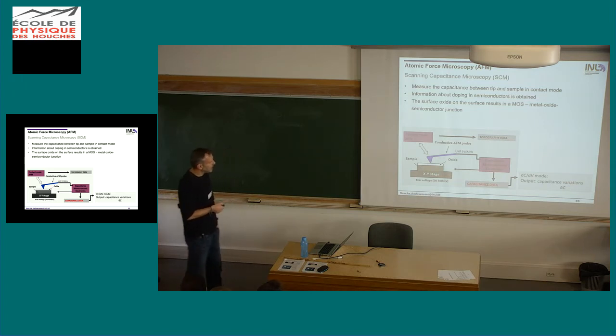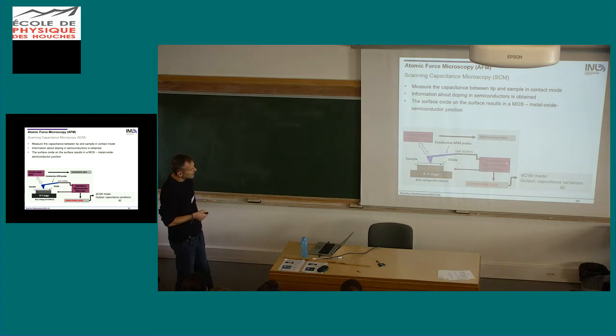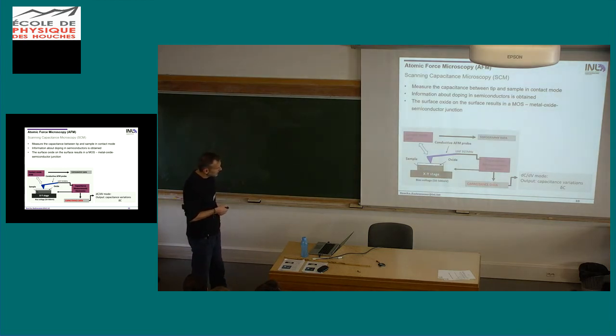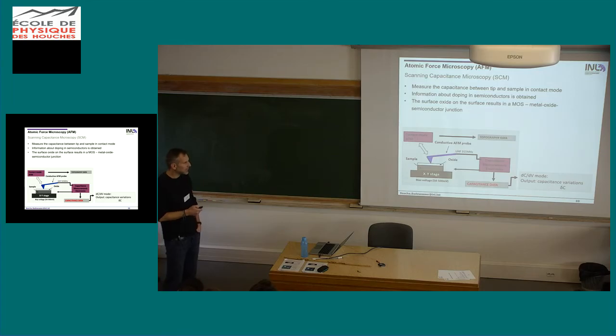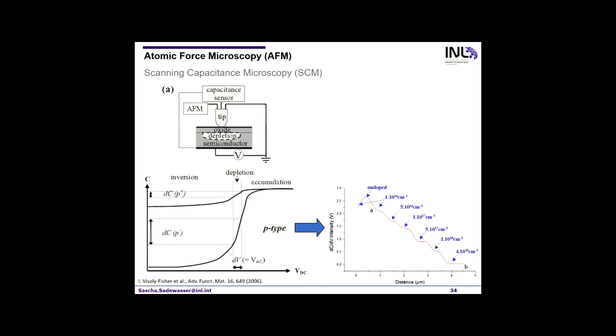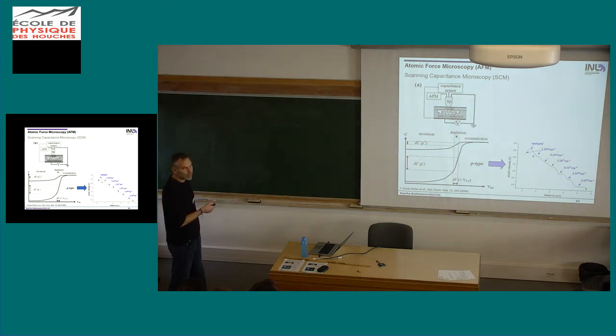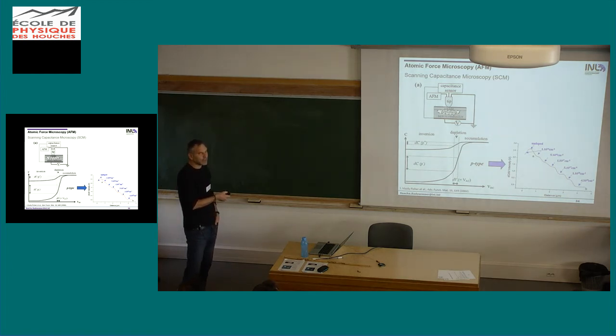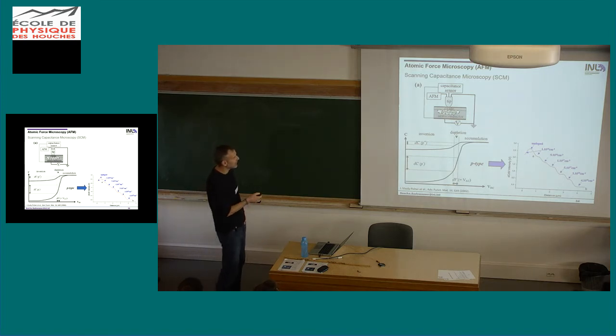What we use here is, in addition to our regular AFM system, some capacitance measurement electronics to extract capacitance data. We have our sample, and we need to have some insulating material and a conductive tip. So in the end, we have a metal oxide semiconductor junction, which we use to then measure dC/dV. We use an AC voltage for this, and we measure the capacitance. So if I have this tip on the oxide and I apply a voltage to the tip, I would deplete the charges around this tip position in the semiconductor, or attract the charges depending on what my majority carrier is. And this depletion region leads to a capacitance.